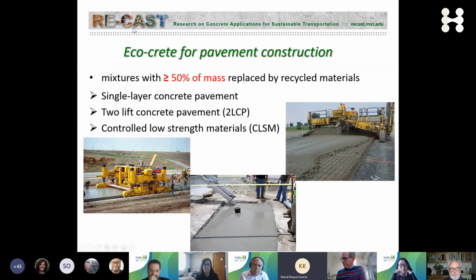And through the RE-CAST Center here at Missouri S&T, we've been working also on pushing the envelope on ecocretes by using highly durable concrete for pavement construction, but also concrete that contains at least 50% replacements of everything: of the sand using recycled materials, of the cements, even recycled water, recycled tires, steel tire belts for fibers. We seek to use it for pavement construction, either single lift or double lifts. This is a double lift here, where you can load the lower lift with higher content of SCMs or higher content of recycled aggregates. And also some of the fines can also be used for controlled low strength materials.